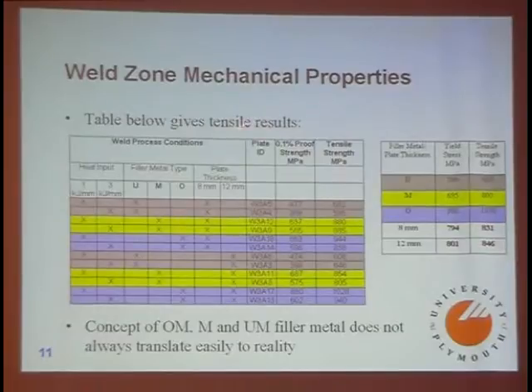So this table gives the tensile results. This is the weld process conditions, heat input, filler metal type, undermatched, matched, overmatched, plate thickness. We measured 0.1% proof strength and tensile strength. This colour here, I'm not very good with colours, I'm afraid. I just choose them. I can't describe them. That colour there is undermatched, the yellow is matched, and what I think is blue is overmatched. And it shows you here the original strength of those filler metals, and there the strength of the plates. And you can then correlate those strengths with these values and those values.